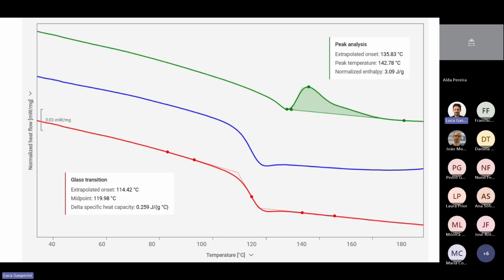But we thought, okay, maybe we could try something slightly different. We will try to fool the material. We will only heat to 120 degrees, but we will leave it there for a longer time, for 2 hours. See if that's fine. And the result you see by the green curve. We then cooled the sample and heated again. And you see at the moment where the glass transition starts, I see another exothermic reaction happening. So the glass transition is not even fully finished, meaning that the isothermal curing at 120 degrees, despite the fact that we took 2 hours, was not enough. And we see a post-curing exothermic reaction, meaning that the curing was not sufficient.